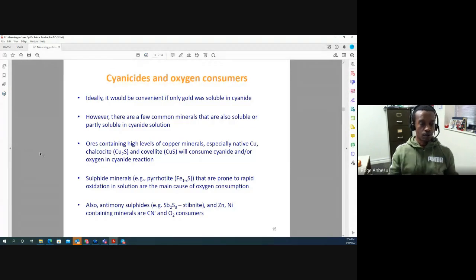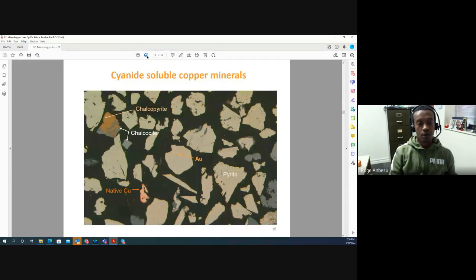So in this case, you smelt, you recover the copper, and from the residue, you can collect the gold as well, and happy days. That should be a lot more economic to run with, rather than just because you say cyanide works for gold, it doesn't mean it works for all gold ores, okay? And as I said earlier, if the material has carbon in it, again, cyanidation is not going to be effective. So that's why we need to first understand the mineralogy before we talk about further processing of the ore itself.